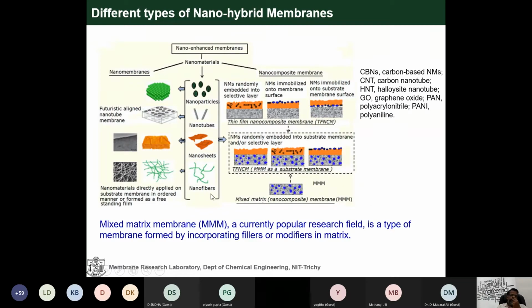See here the information. If you look at gas separation or any kind of gas sensing, what kind of materials are we looking for? Materials uniformly distributed in the polymer matrix. Nanoparticles, nanotubes, nanosheets, nanowires have different ways: they are randomly embedded into the membrane surface, or immobilized into the membrane surface, or immobilized into the substrate and internal pores of the membrane. Due to that, you can alter the properties. So what are the functionals? Polyacrylonitrile, graphene, polyethylene, halloysite nanotubes; different kinds of mixed matrix membranes are developed using these.